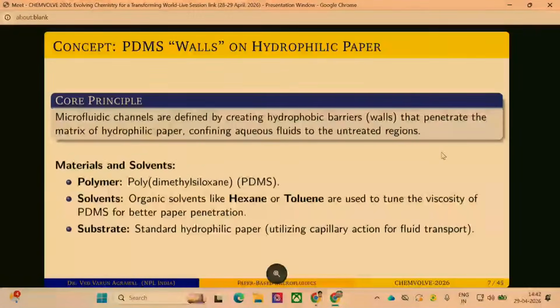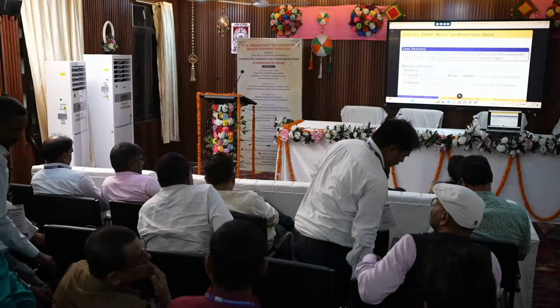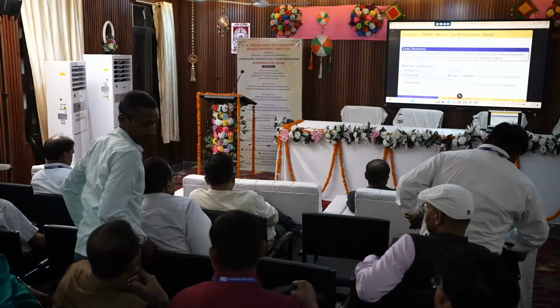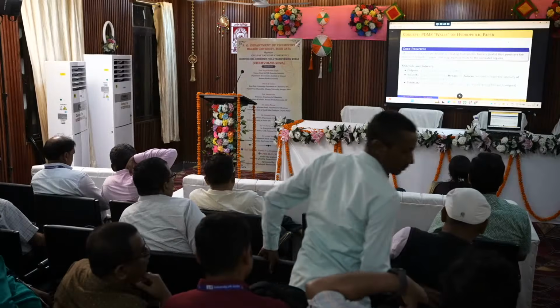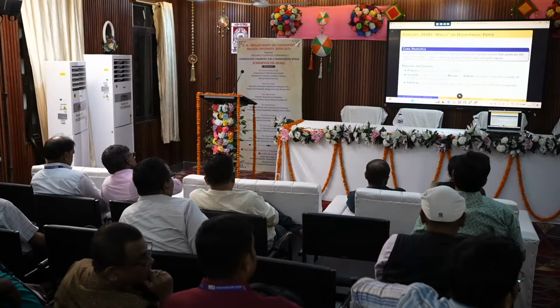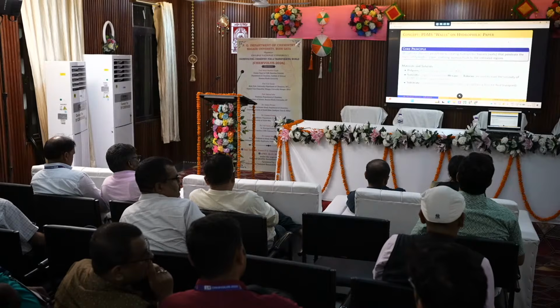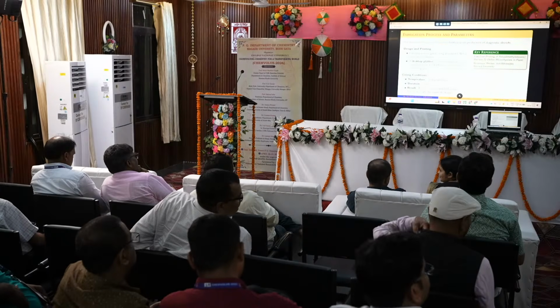So for these walls, you need something which is hydrophobic, and we thought of PDMS, not just we actually. This work was first done by Whitesides and they used PDMS, so we are also using PDMS. But PDMS is very thick. So you need to dilute it, because if you want to write it, you should have a carrier organic substance, something like hexane or toluene, which reduces the viscosity. So it has to be mixed in a certain ratio. Again, one has to figure out what ratio is appropriate. So this is a subject of study, and then you create hydrophobic channels.